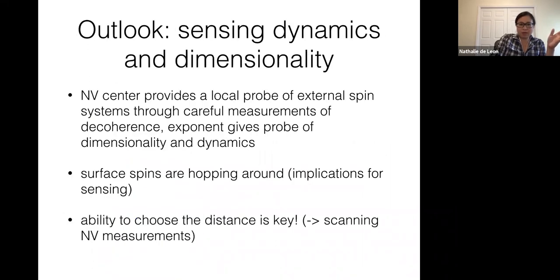What I've talked about is that the NV center is a nice local probe of these external spin systems. If you just do very careful measurements of the decoherence, and in particular, what we've shown here is that even just looking at the stretched exponent gives you this nice probe of the dimensionality and the dynamics of this bath. In terms of the microscopic details of what we learned about surface spins, we showed with this probe that these surface spins are hopping around. And again, just to emphasize this, the reason that the NV center is a particularly interesting probe is that you have this ability to choose a distance away from your system. So this has direct implications in applications towards these nice scanning NV measurements that several groups have.